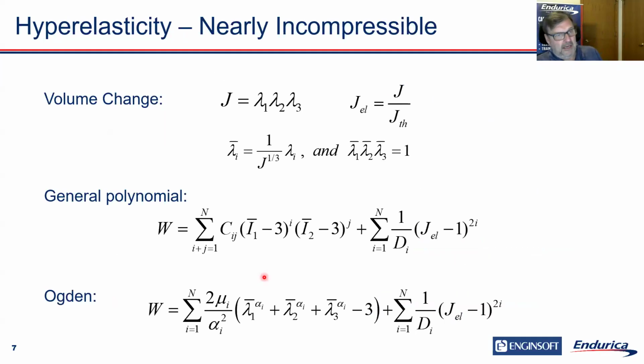Okay, it's often very hard to change the volume in rubber, so we treat it oftentimes as nearly incompressible. Sometimes people treat it as exactly incompressible, but in finite element models, sometimes that creates convergence problems. So it's best oftentimes to have some amount of compressibility, but we do that by treating the compressible part and the incompressible part separately. So we characterize the volume change by a parameter called J,